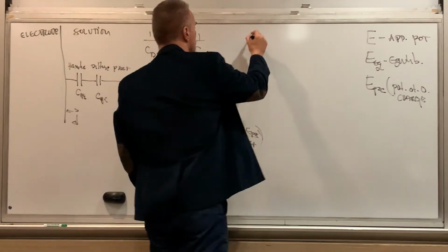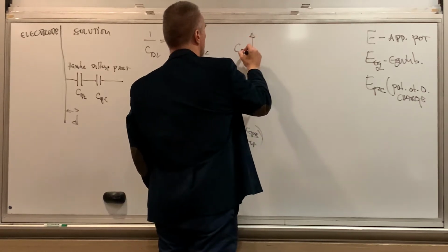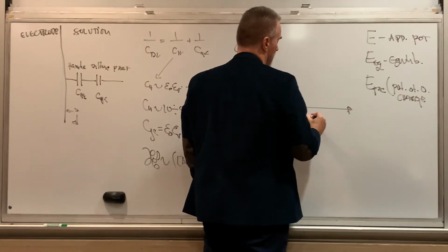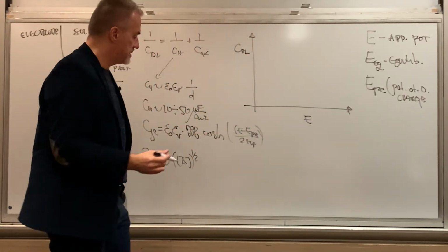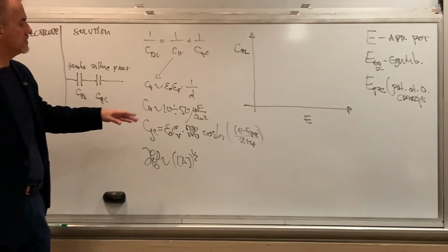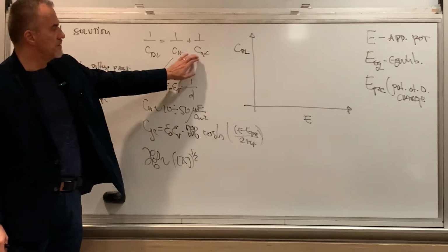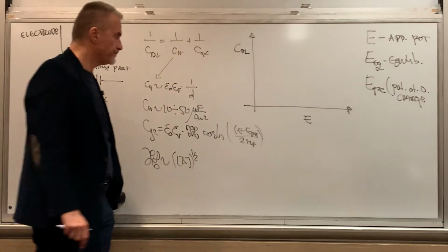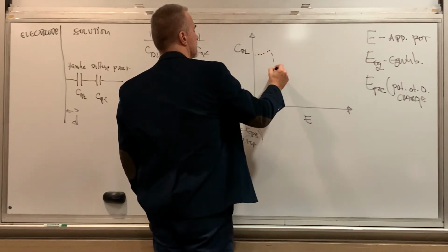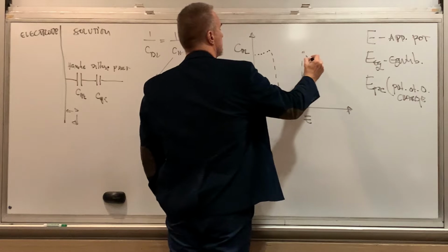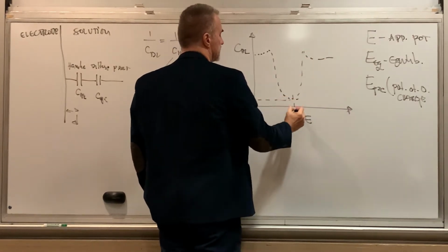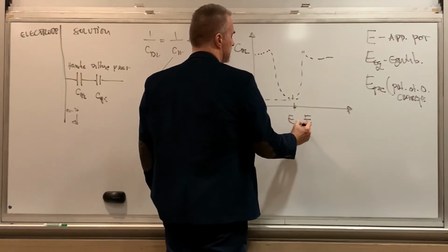And what is important, we said, if we measure the double layer capacity of our electrode surface as a function of the potential, and let's say we are looking at this when we have a low concentration of the electrolyte, which means the Gouy-Chapman layer determines how this really looks, then we have something that looks like this, and this minimum in the capacity, I'm going to call C minimum, is at E PZC, right?